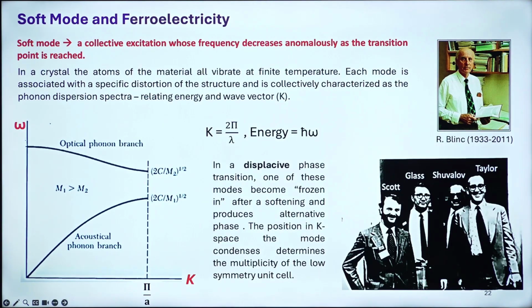Fine. So then what is the link between the soft mode and ferroelectricity? Is it a signature that there could be a structural transformation in solids when you have a soft mode, a collective excitation whose frequency decreases anomalously as the transition point is reached? This is not only restricted to temperature, we do see this kind of thing even with pressure. When you apply pressure on a system, the phonon frequencies respond to the pressure, and we do see soft modes even then, but one cannot expect ferroelectricity there. Rather we expect a structural phase transformation, which is purely driven by the phonons.